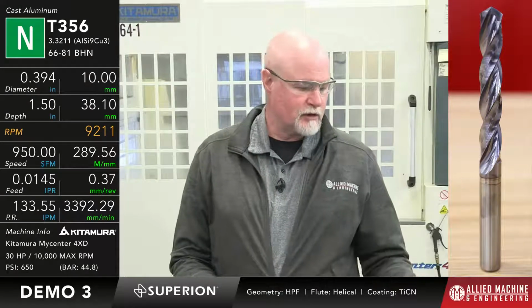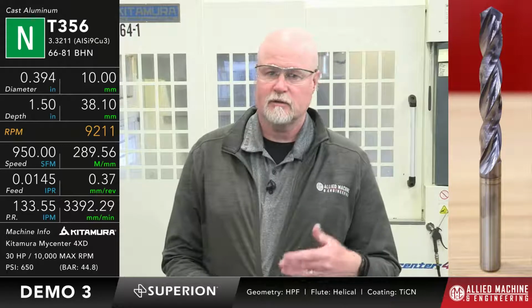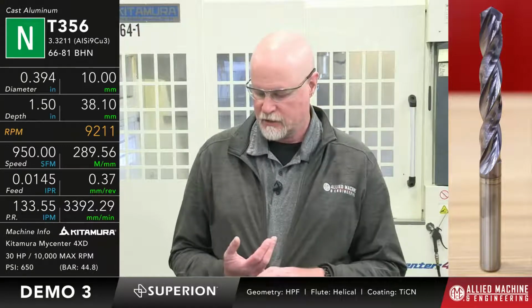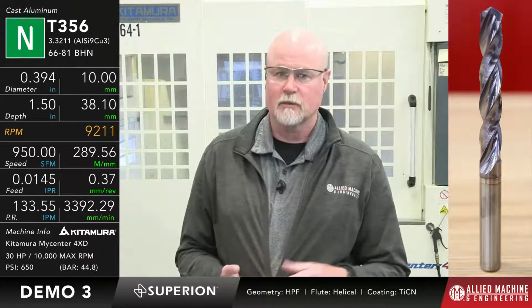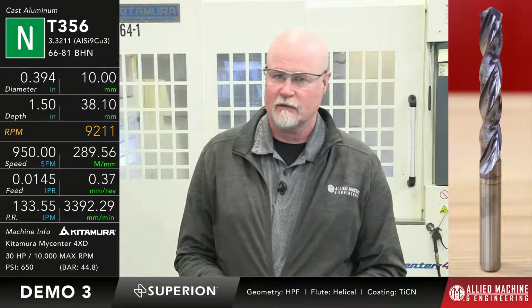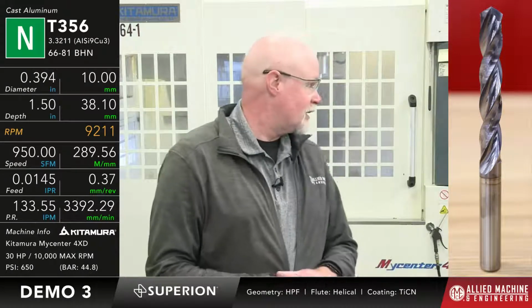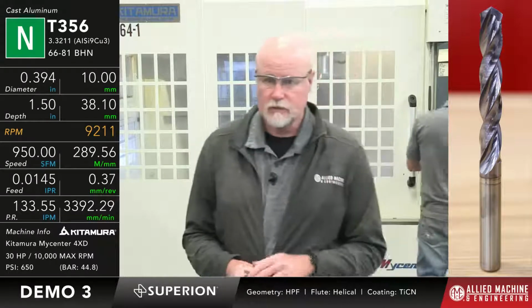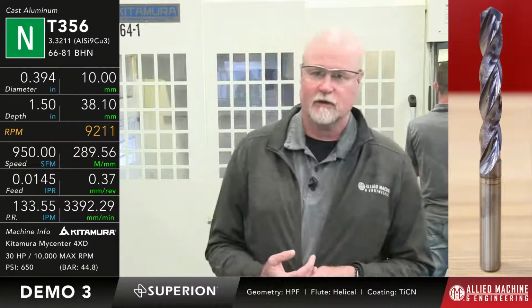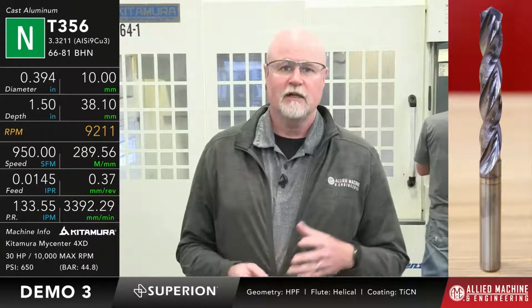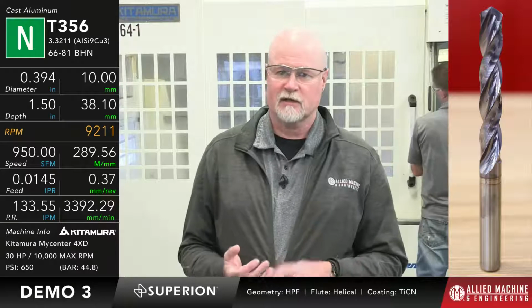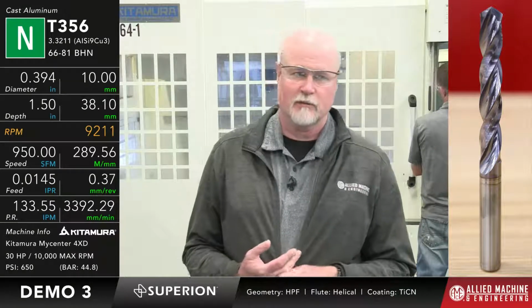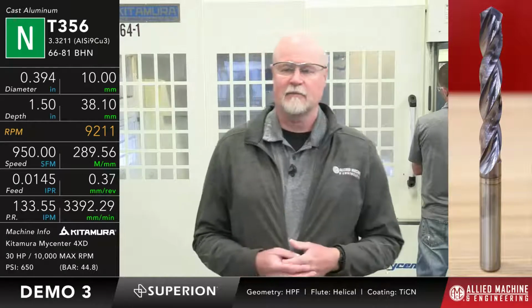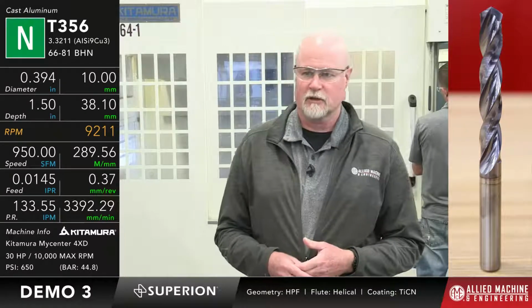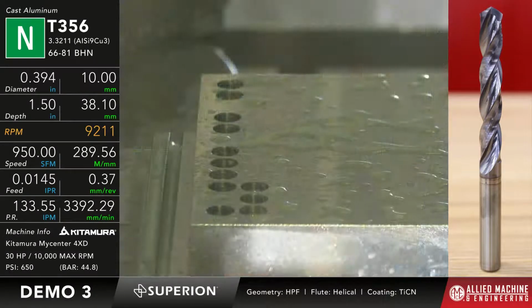Once we're done showing you the chips though, we do have the material that we ran, the stainless and the hardened steel, and we'll get the piece of aluminum out so we can take a look at what the hole quality is after we're all done with this. So Dave, if you're ready, let's go ahead and run this aluminum. Once again, 10 millimeter diameter going an inch and a half deep, 950 surface feet a minute, 14.5 thou per rev. For our friends that live in metric land, that's 10 millimeters diameter, 38.1 millimeters deep, 289 meters a minute, 0.37 millimeters per revolution. So let's take a look at what this does.